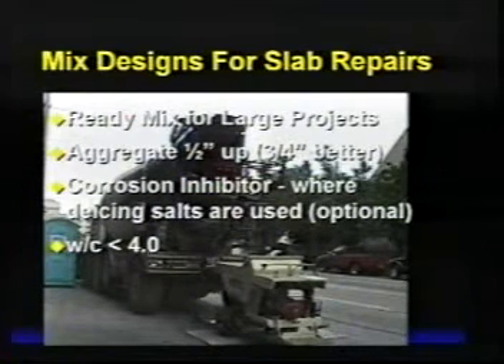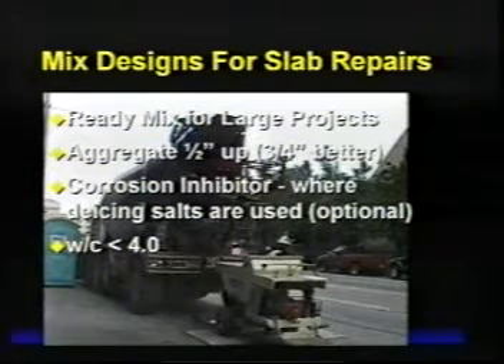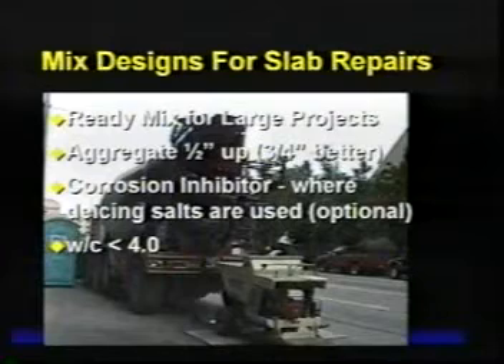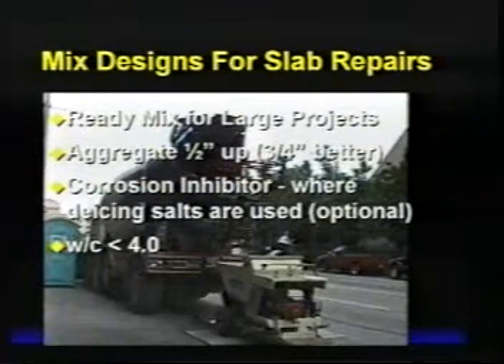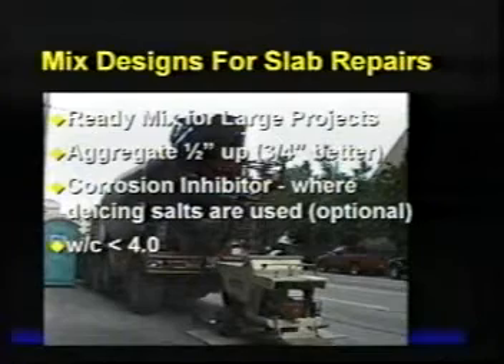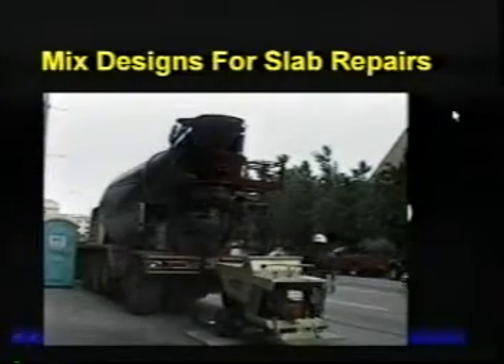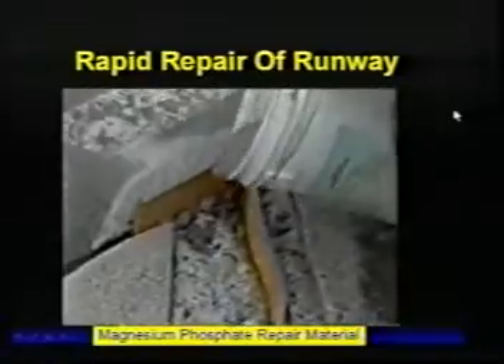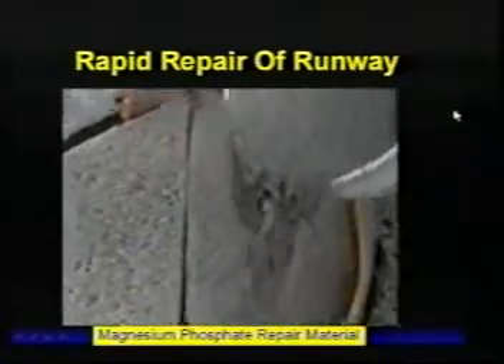The mix designs that are recommended here are, in traditional ready-mix applications, a minimum of half-inch aggregate. One of the industry trends is to go with pea gravel. That induces more shrinkage. The real recommendation is to use 3/4 inch or higher. If you can get 1 inch or 1.5 inches for some of these thick repairs, you're going to cut down the amount of shrinkage. A water cement ratio less than 0.4, not 4, sorry. But for a lot of horizontal repairs, prepackaged materials are applicable.